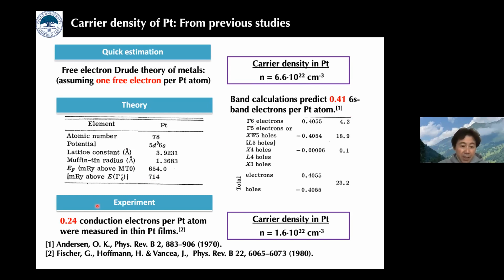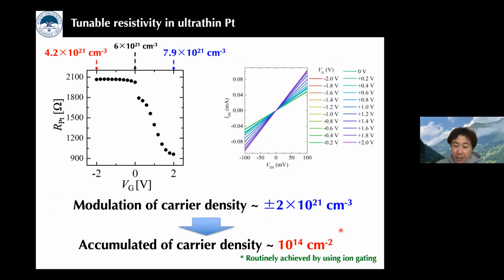And experimentally, this theoretical calculation is supported, and only 0.24 conduction electrons per platinum atom were measured in their experiments. In their estimation, the carrier density is 1.6 times 10 to the 22nd per cubic centimeter. And in our case, 6 times 10 to the 21st, not so large a difference. So in this sense, we can say this is a reasonable value.